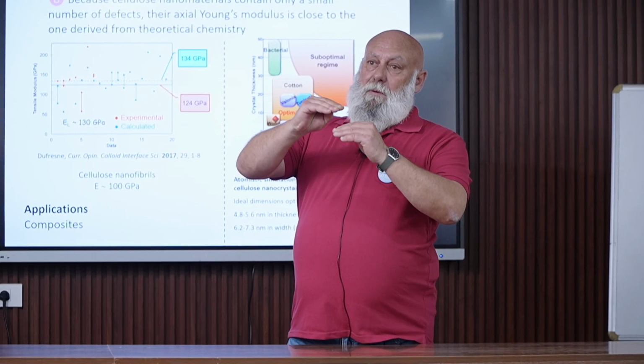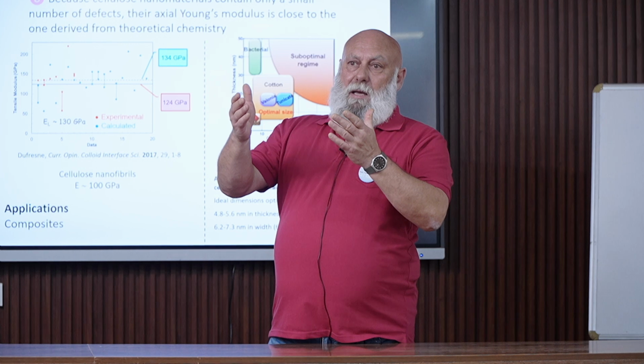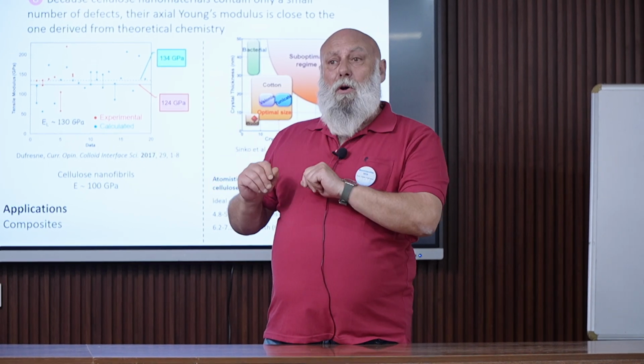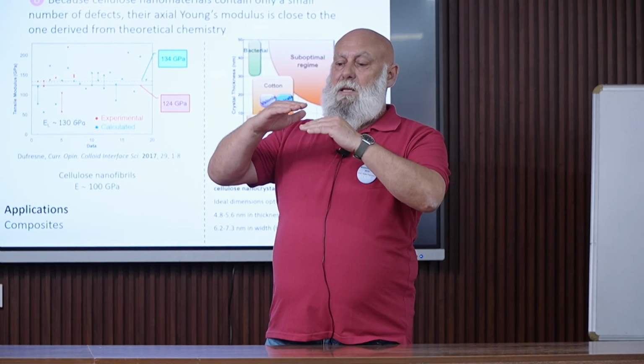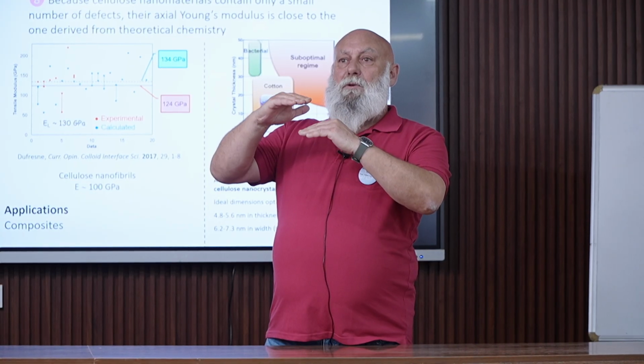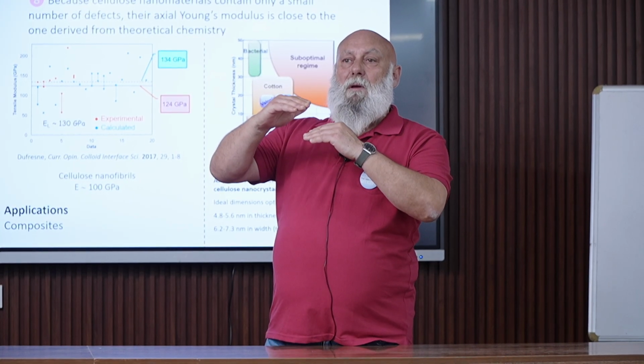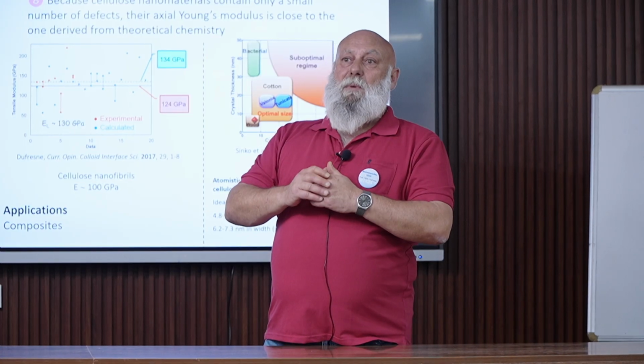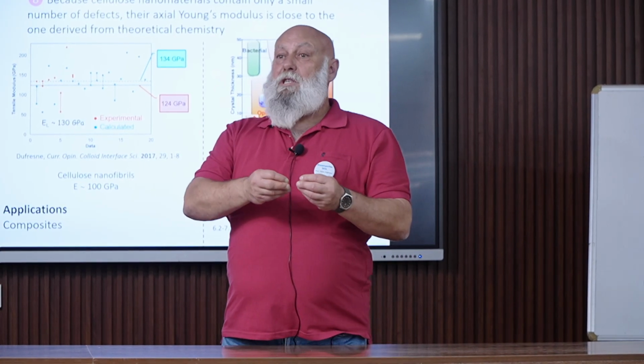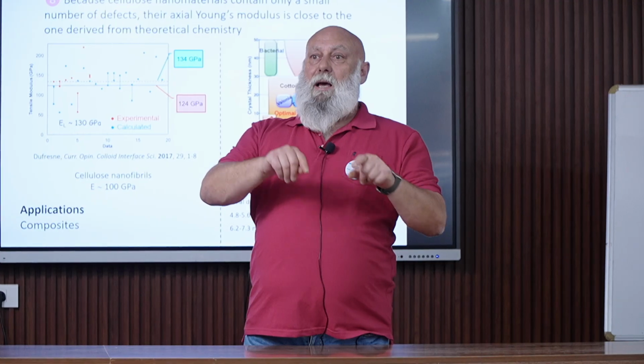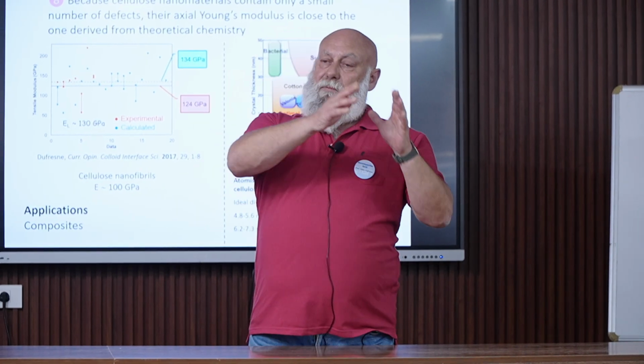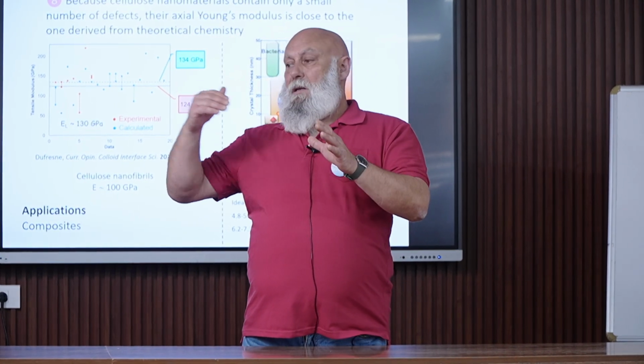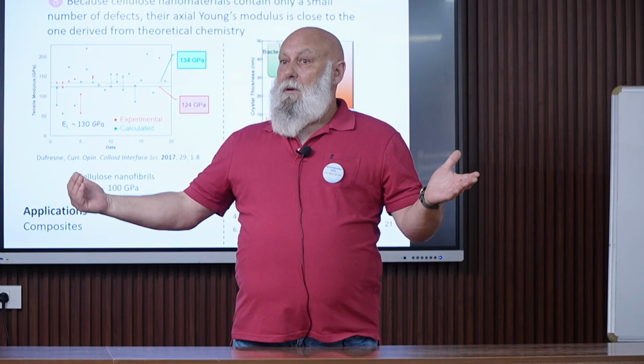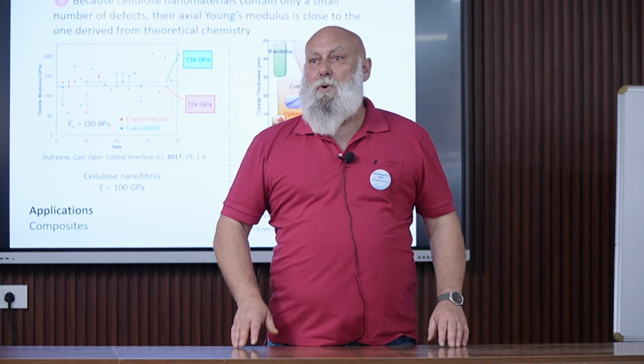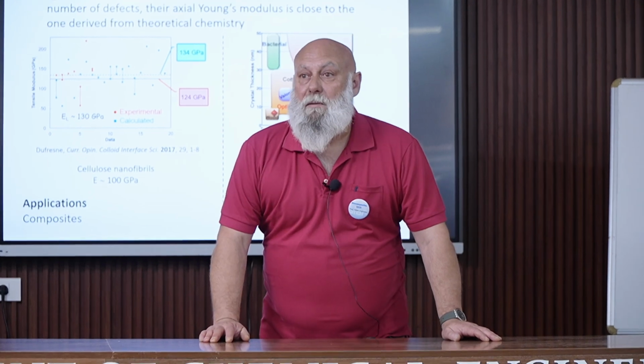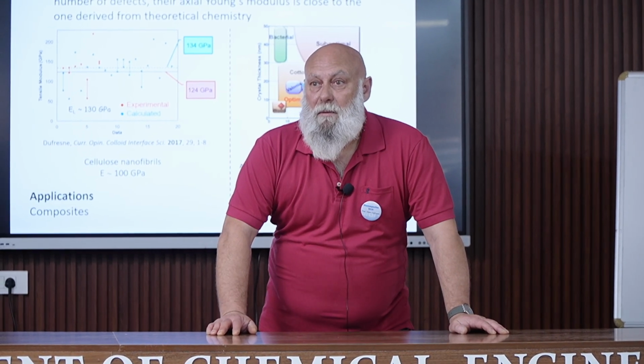The signal obtained by X-ray diffraction comes only from the crystalline domains. So they can determine the strain or the deformation of the crystalline part of the material. Of course, the force is applied on both the crystalline and the amorphous domains, so they have the force applied to the crystalline domain and the deformation of the crystalline domain. They can plot the stress-strain curve of the crystalline domain, and then the modulus. Okay. Thank you.